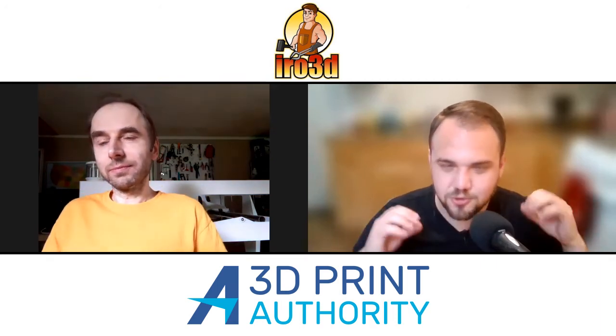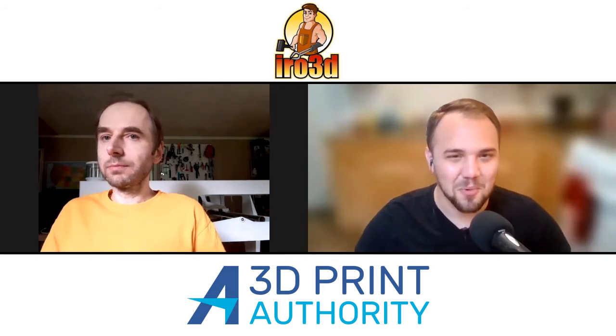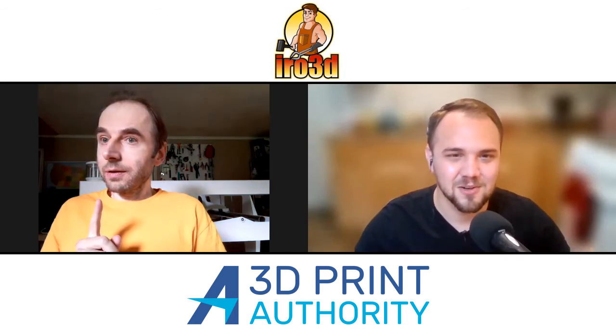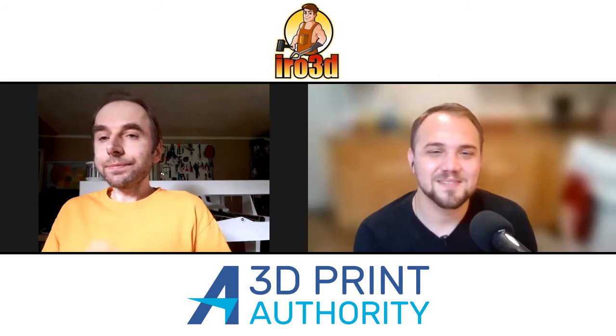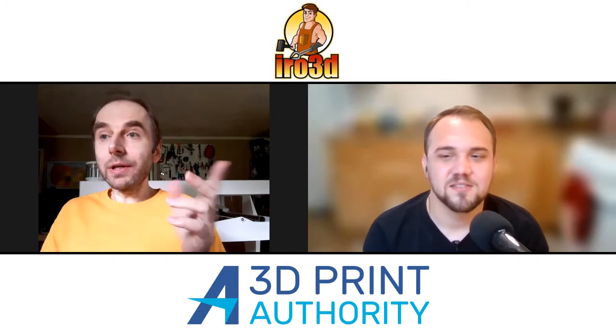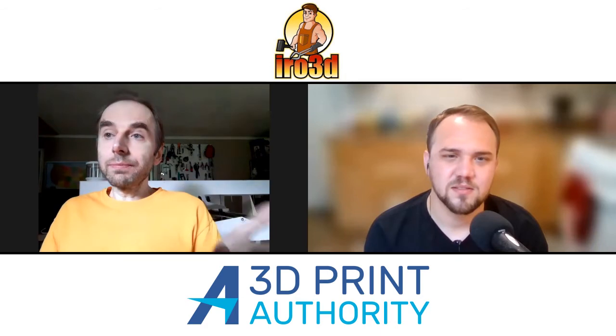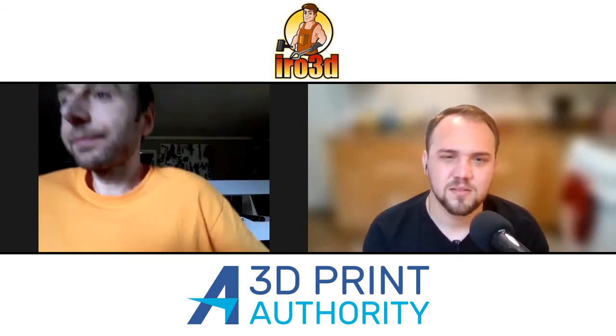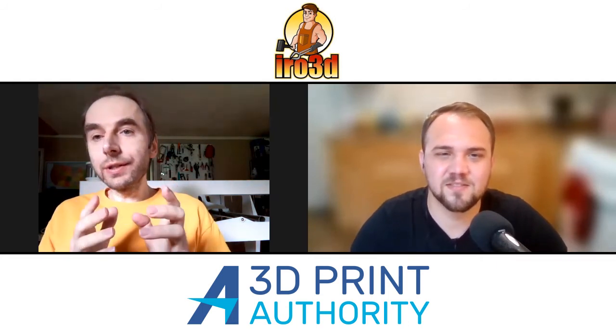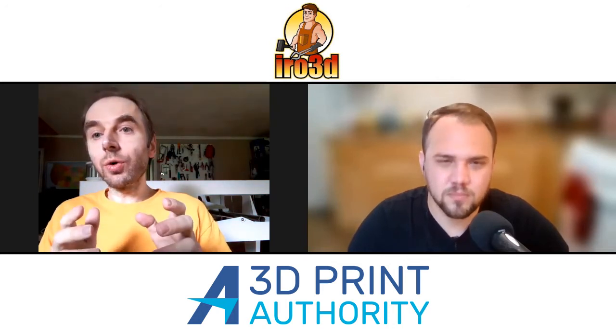So what's interesting to me about your process is that the metal isn't sintered, which is much different from a lot of, if not every other, metal 3D printing process. What's going on there? Yes. So there are several ways to do it. The first method I thought about would be infilling with the liquid metal. And I think it's pretty much the best method because you have no sintering and there will be no shape distortion and no shrinkage.